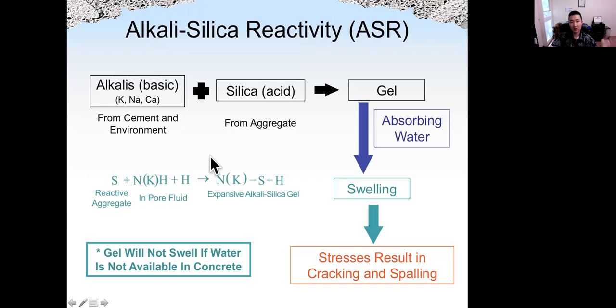So ASR is caused by alkalis, different types of alkali: potassium, sodium, calcium alkalis. They are going to generate different types of gels. The silica is coming from aggregate. So alkali plus a certain type of silica plus water will cause swelling alkali silica gel. That swelling will result in cracking and spalling of concrete. And remember, the gel will not swell if water is not available in the concrete. So as long as there is no water in the concrete, even if we have a lot of alkali and reactive silica, there will be no ASR.